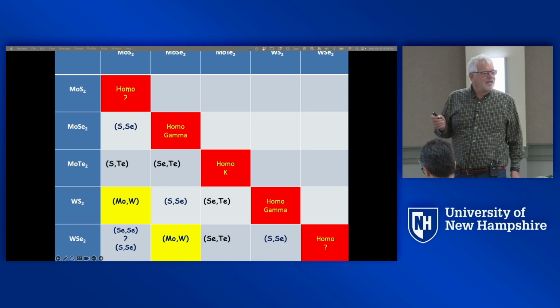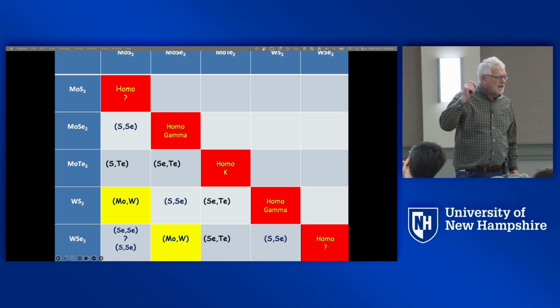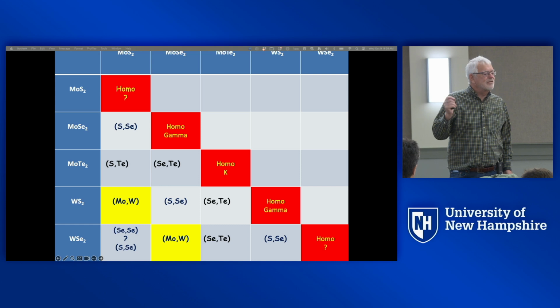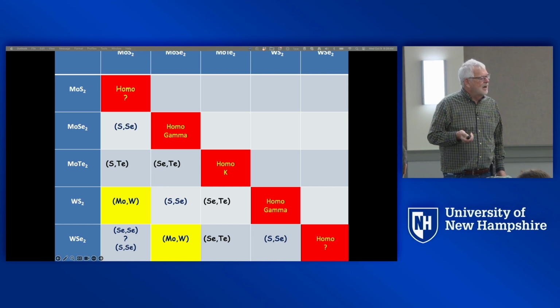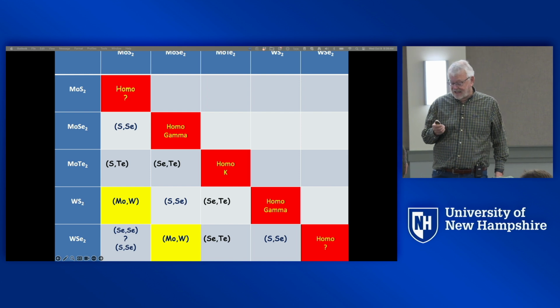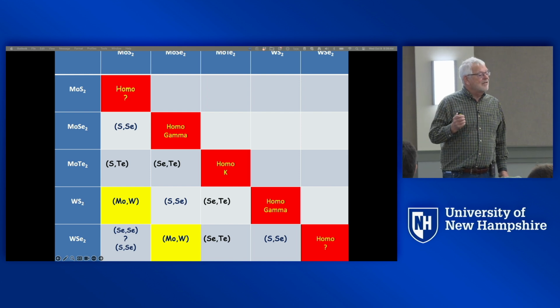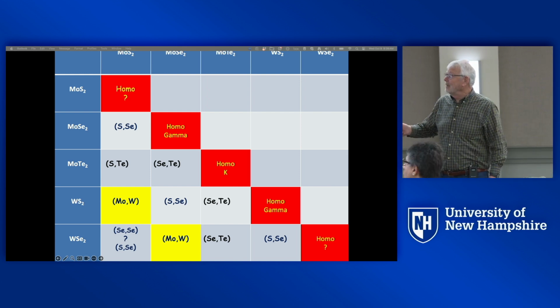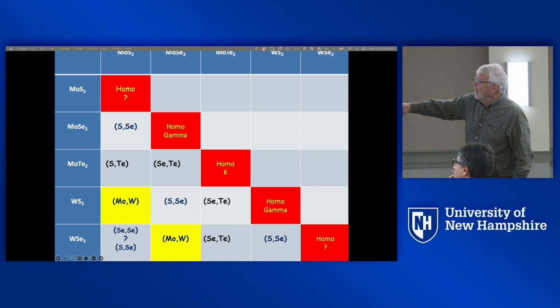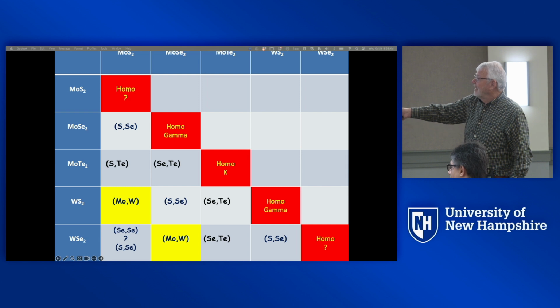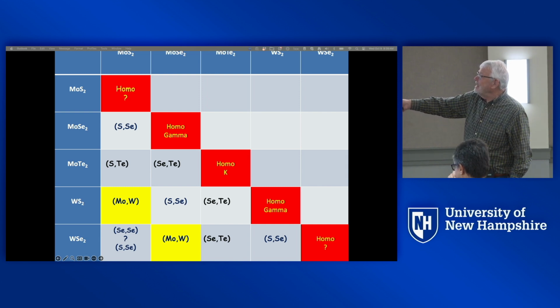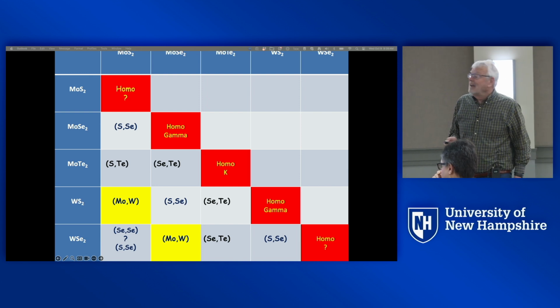These are the electronic structure, energy versus momentum, of a single layer is what I showed you in the first slide. In a single layer, the top of the valence band is at the K point in the Brillouin zone. And from these 5 materials, you can make, I guess, 15 different combinations and make Moiré patterns out of them.